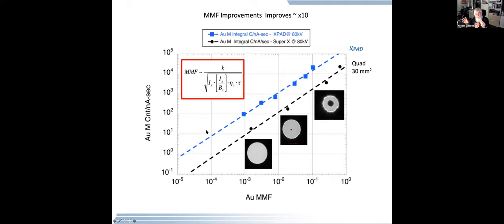I did a very simple experiment. All of you can do this. I take single nanoparticles of gold. We can measure the size of that particle. We can put it in the beam. We can support it on a substrate. So I know the size of the particle. I know the area being illuminated. I know the total mass of the particle in the background. And I can measure the minimum mass fraction that's contained in there. So if I had just a nanoparticle by itself with nothing else, the mass fraction is 100% or one, okay?